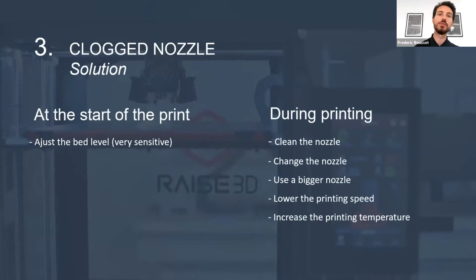For this issue, I will separate it in two parts. For the first one, if your nozzle is clogging at the start of your print, this means that your bed isn't adjusted well enough. For polymer filaments, it is quite easy to find the bed level, but for metallic filaments, it is quite sensitive, as well as the tightening of the screw. Metallic filament is a bit more sensitive, so the bed level requires a bit more experience, but it isn't quite hard. After a few prints, you should be able to find this problem. But yes, if your nozzle is clogging at the start of your print, it should be the bed level that has a problem.